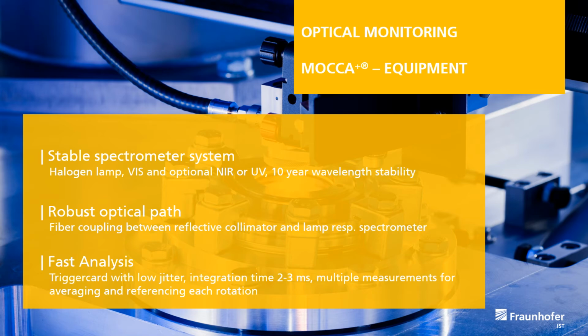Measurements are available for every turntable rotation. In our case, at 250 rounds per minute, this means every 240 milliseconds. All 3 parts of the transmittance measurement, reference, dark, and sample, are made each rotation. The typical integration time is 2 to 3 milliseconds. This means you get your thickness evolution in very small steps.